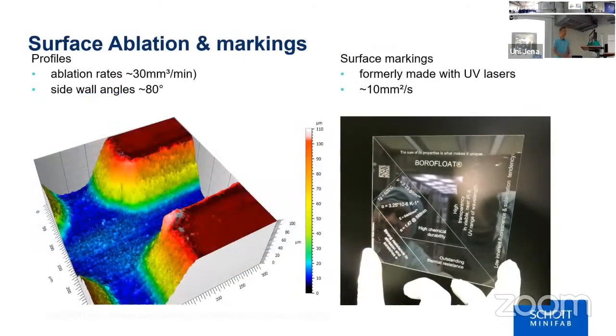Let's first start with the ablation. With ablation, you make some profiles with certain functionalities, certain properties, depth. We have a limitation of the wall angle. The wall angle is typically in the order of 80 degrees. We have achieved very high ablation rates, up to 30 cubic millimeters per minute. And there you can do quite strong material removal. What we use in daily life is